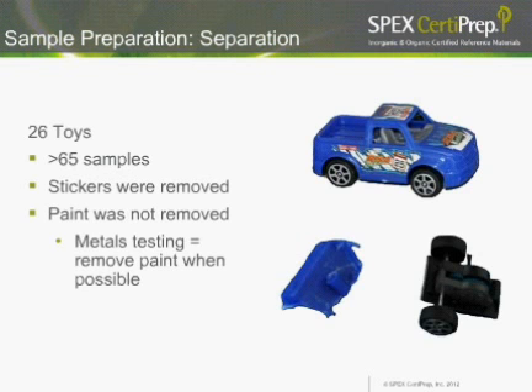As I said on the earlier slide, one of the first things that we had to do was separate these toys into component parts. To us, it was possible that this toy truck here had several different types of polymer or plastic, and we wanted to test each grouping as a separate sample. So we had 26 toys, which in the end turned into over 65 different samples. For this toy, we removed the stickers, but we did not remove the paint. And if you were going to follow up an analysis for metals, it might be part of a metals procedure to remove the paint and use that as a separate testing sample.